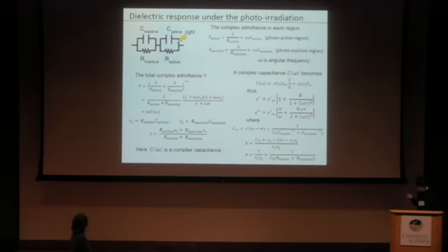In this case, the energy of light source is 3.4 electron volt, and the band gap energy of lanthanum aluminate is 5.6 electron volt. The number of photoexcited carriers is extremely low, and so I think that conductivity is low under the photoirradiation.